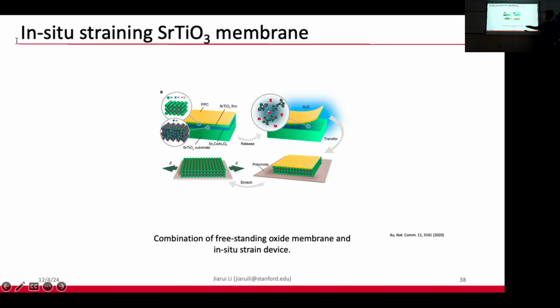And when we dissolve this intermediate layer, we can release the top layer that we want into the water, and they are 20 nanometer thin, like few nanometer thin, and millimeter sizes, so that we can manipulate them as what we do in 2D materials. Like we can transfer them, stack them in different geometries. But in this study, we try to laminate this strontium titanate on a polyimide thin film. You can think of it as a plastic, and it's soft and it's stretchable, so that we can apply strain very easily.